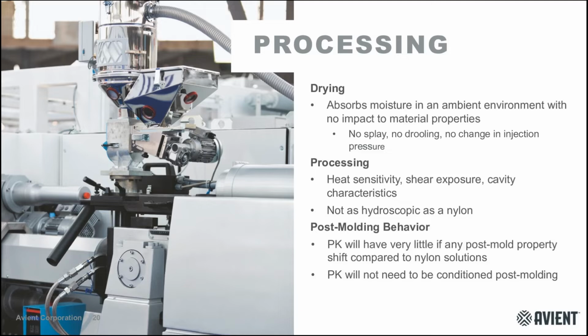So now talking through the actual process of the material, how does this material perform? How does it handle? How does it compare to that of nylon solutions? The way that I like to put this is that polyketone typically performs better and is easier to process than nylon. It is not as sensitive in terms of the viscosity of the material causing you issues. The material has great flowability, great compressibility in the cavity. The only issue that we tend to call a negative, but it's not necessarily negative, you can see this with all materials, is that it is generally less thermally stable in a molten state when compared to other materials that you more commonly would use.